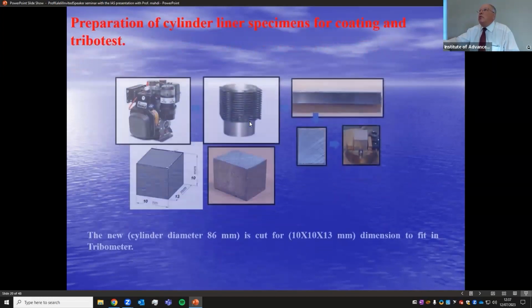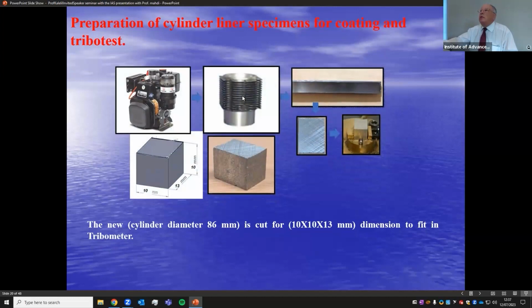And what we did, for the tribo test, we cut it without damaging the rubbing surface, the honed surface. We cut a 10X10X13 millimeter dimension to fit in the tribometer here. This is the cylinder liner surface.